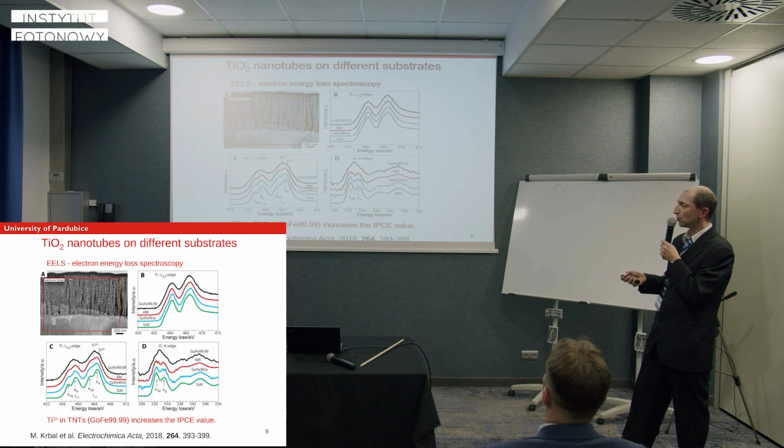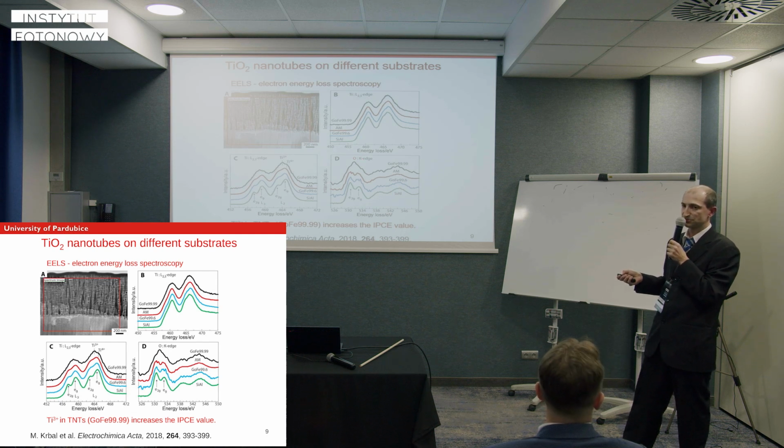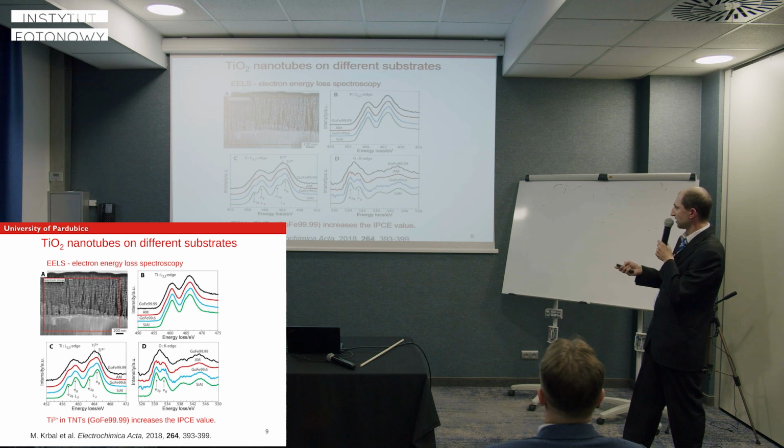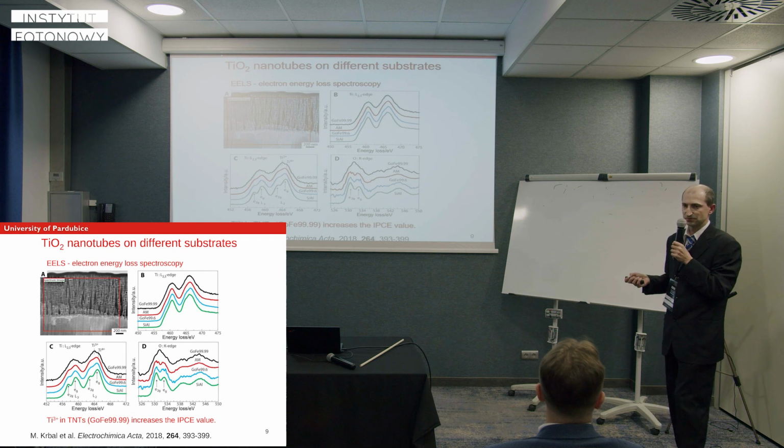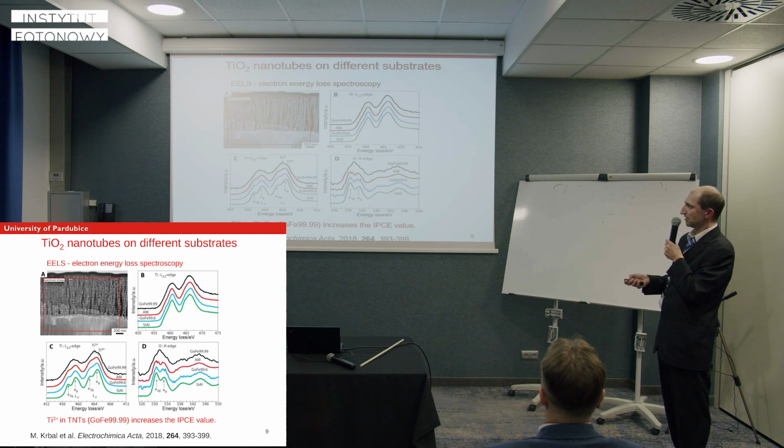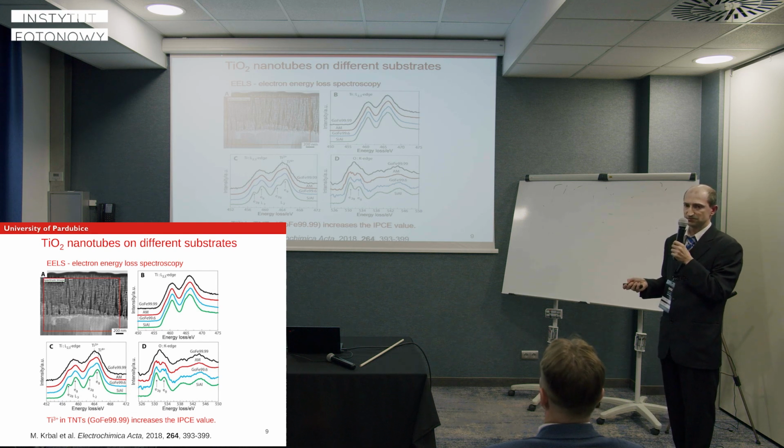So it's a doped structure. This is also seen in the oxygen K edge, and it is the same story. This is the typical anatase splitting on the oxygen K edge, and this is the doped structure, so there are oxygen vacancies. So we can conclude that the excellent photocurrent for the Goodfellow is due to titanium 3+ embedded in the structure.